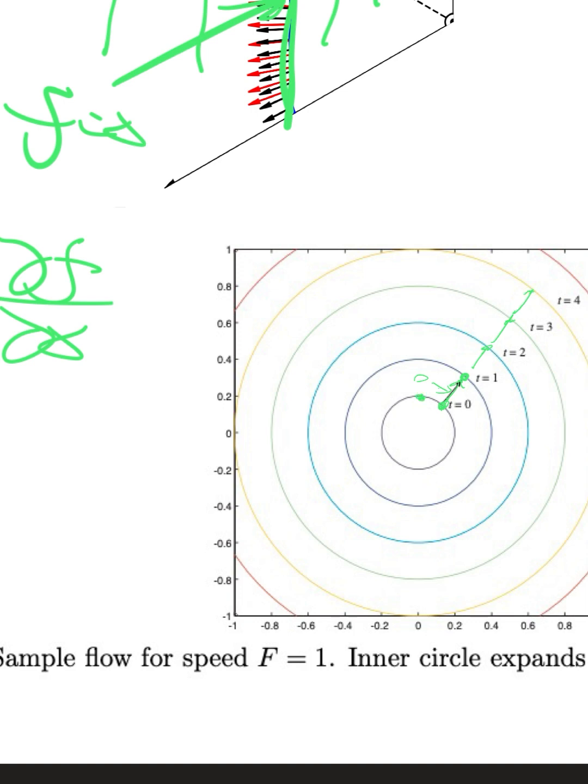And if I have a point here, I can use the normal to keep extending the point. If you're pointing outward, eventually you get a lot of points, and except for this f equal to 0, you can simply use the distance here as the value of this point, right? You see what I mean? So f would simply equal the distance here. Then I assign this point equal to the distance here. So f of another point is equal to d2, and so on and so forth. So I can populate the entire point cloud in the normal directions.